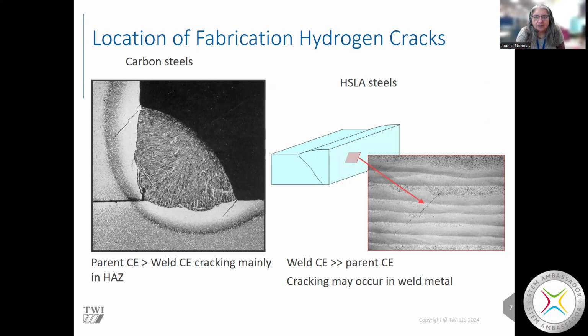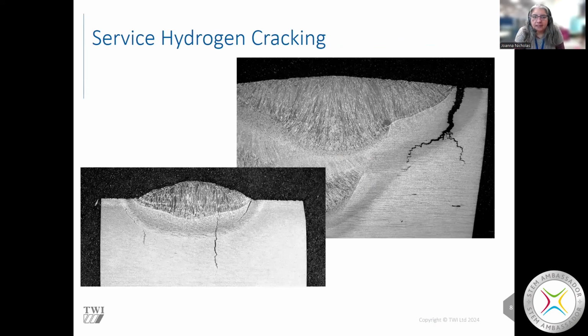I also said that service hydrogen cracking has a much lower hardness limit, down to 250 Vickers hardness. And that can occur anywhere in the weld zone. It's usually associated with the heat affected zone, but it might not be immediately close to the weld. It might go on into the parent material. It's usually a bit branched and looks like a tree because of the way the cracking happens.